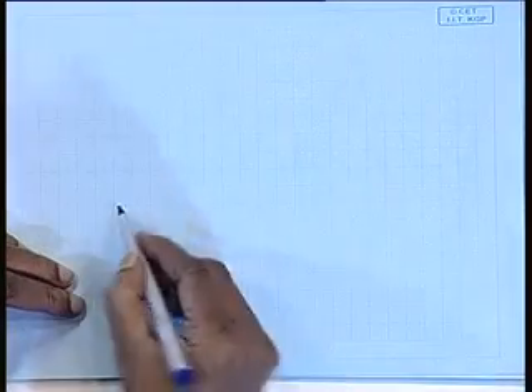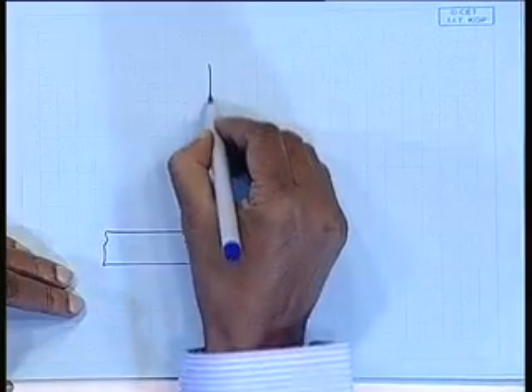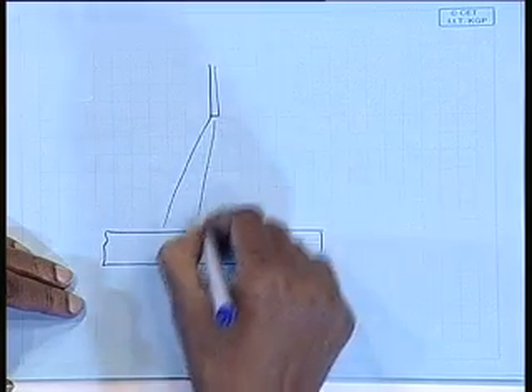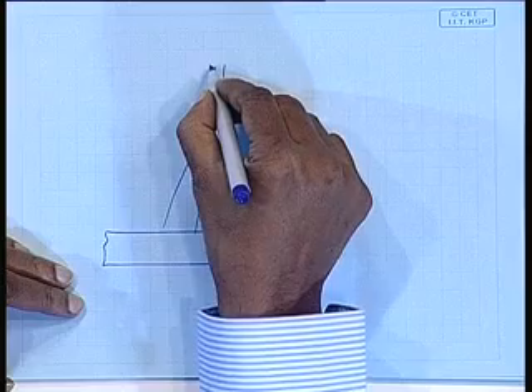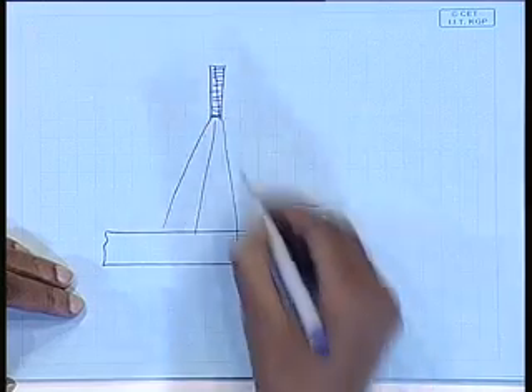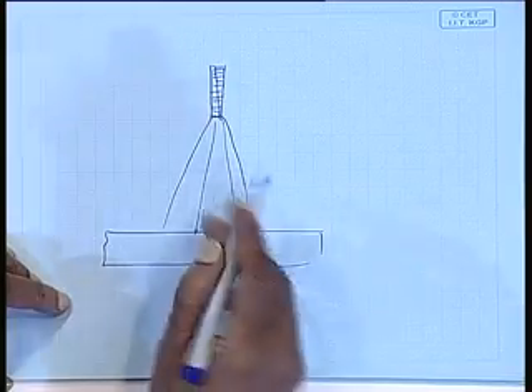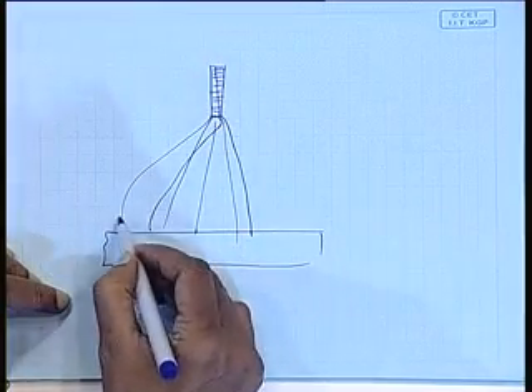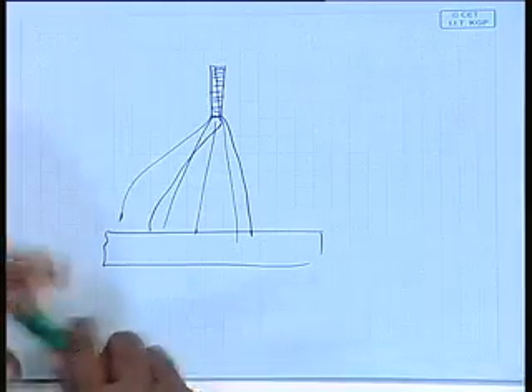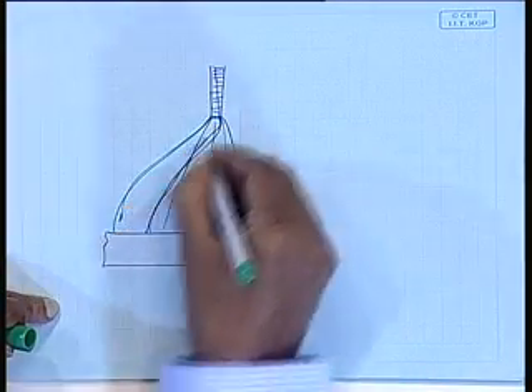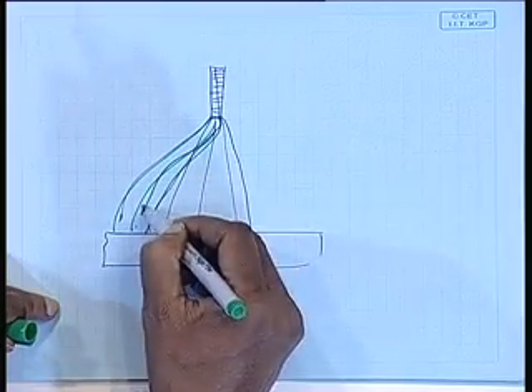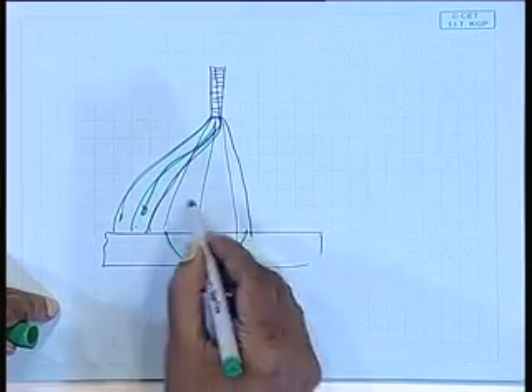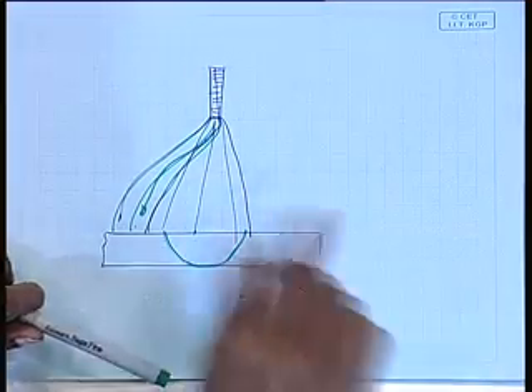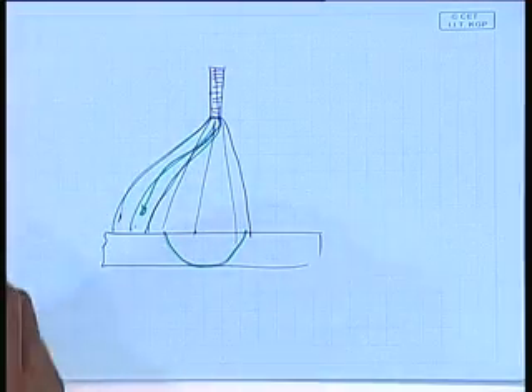The longer it is, the chances of deflection are more. That is called arc blow. If the arc column deflects, suppose, say, purposely I am drawing a much longer electrode. In the magnetic field, it may get deflected like this, right. The whole arc column may get deflected. Now, if the arc column gets deflected, the metal transfer also will get deflected. So, you will have to deposit here, it will not deposit there properly. So, metal deposition becomes erratic. So, this phenomenon is called arc blow.